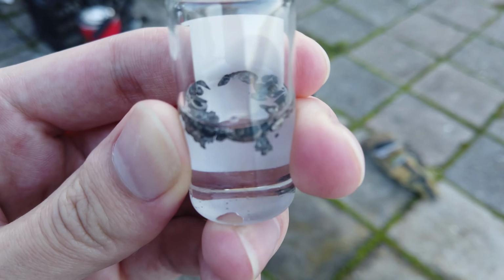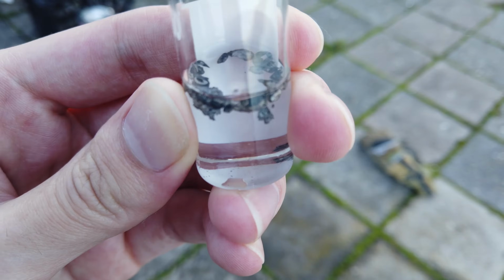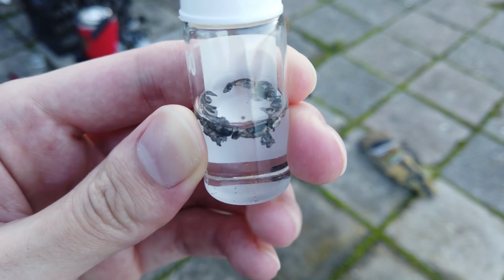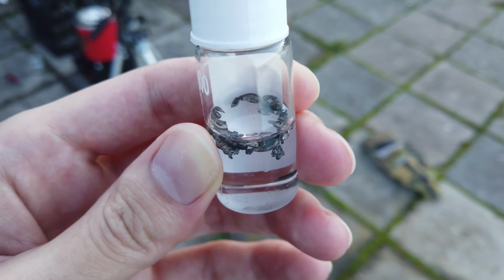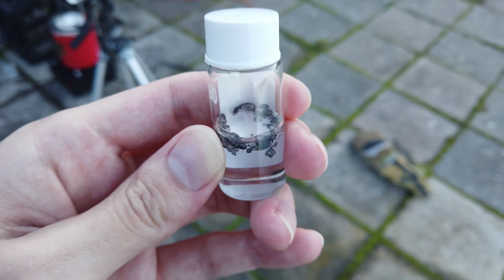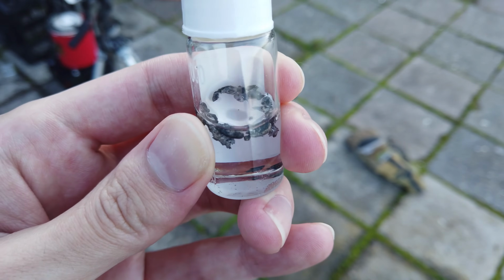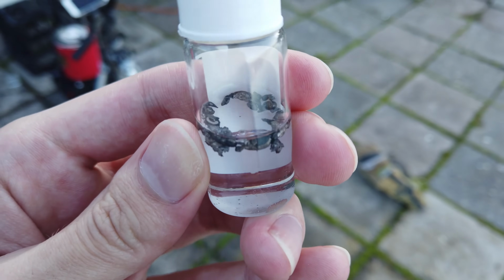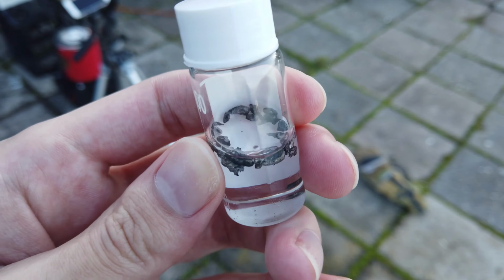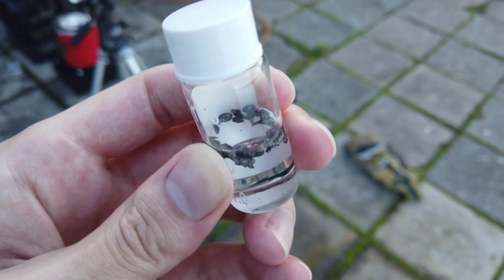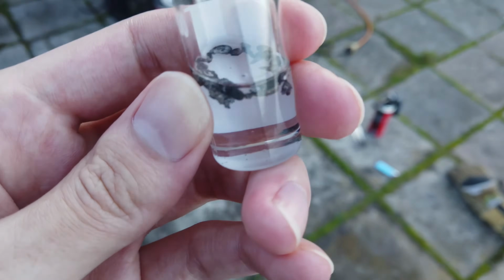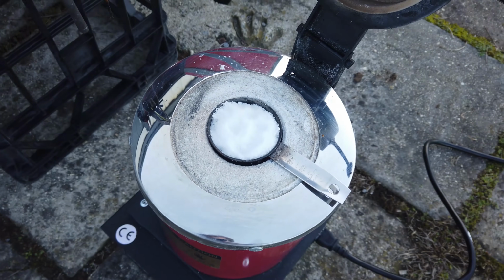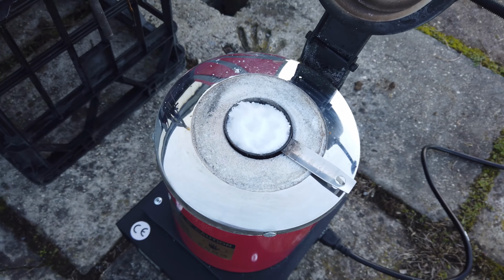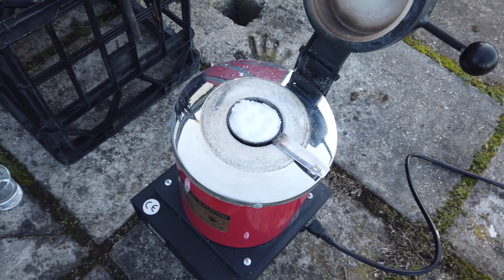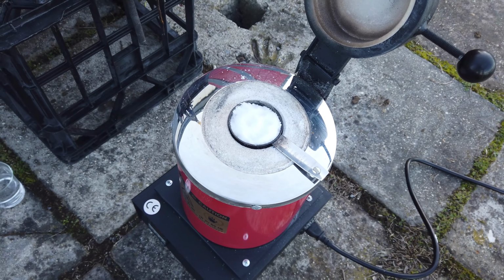It's a bit dirty, as you can see, and I wasn't actually able to melt it all into one chunk. I could melt it into one solid piece, but then I couldn't pour it out of the spoon that I was using to melt it all down in. So it was a bit of a disaster. I'm pretty sure I lost about half of the lithium that we extracted, which is very disappointing. So as a result, I'm actually going to try again. You can see I'm now melting down another lot of our eutectic mixture, and then we're going to electrolyse that to try to get some more lithium.